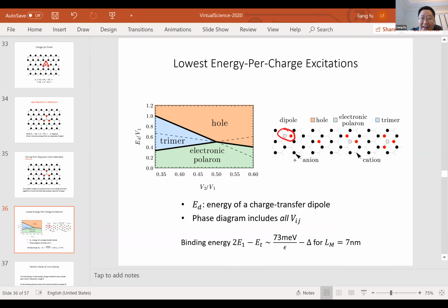So without any interaction, the energy cost of a charge transfer dipole is just delta. But with the electrostatic interactions, it includes 2 times V1 and so on. So all the long-range interactions renormalize the energy of this charge transfer dipole from delta to a new quantity which is called ED. Once we write the results in terms of ED, this phase diagram is exact for all kinds of interactions, as long as the ground state at n equal 1 is this charge transfer insulating state.